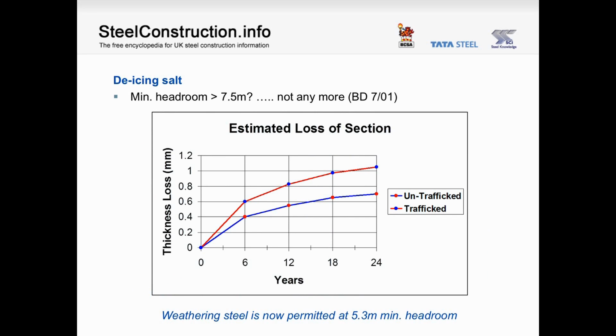This last point is worth dwelling on, because in the past there was a minimum headroom limit of 7.5 metres for weathering steel bridges over roads. That was due to concerns about the build-up of salt deposits from spray. However, part of the TRL study that I mentioned earlier also found that whilst bridges over traffic roads had corrosion rates that were higher than bridges over, say, rivers or floodplains, they were still sufficiently low that you could have a 120-year design life with a sensible corrosion allowance. So, in 2001, the Highways Agency published their document BD 701, and this removed the 7.5 metre headroom restriction. So now, weathering steel can be used at conventional minimum standard headrooms of 5.3 metres.